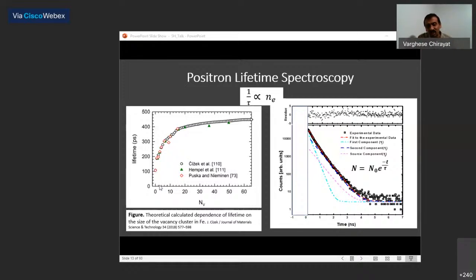Now, as soon as you introduce defects, which has the characteristics of a mono vacancy, that is, it is missing only one iron atom, then your lifetime increases to close to 190 picoseconds, right? And as you go further on, as you keep increasing the size of your vacancy, you can see that your lifetime increases. Now, beyond a certain point, you cannot see a variation in the lifetime.